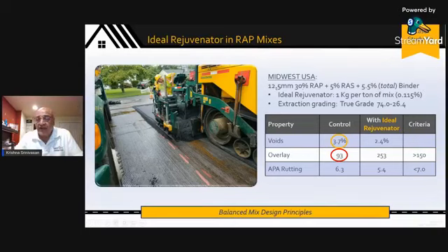Just to give you an idea how much rejuvenator you're adding for 1 ton of such a mix, you're adding about 1 kilogram. And what do you see? These are the control properties, and these are with the rejuvenator properties. You can see the overlay is the test technique that's used to characterize fracture toughness, fatigue resistance, etc. APA rutting is the test technique used to characterize the rutting resistance.